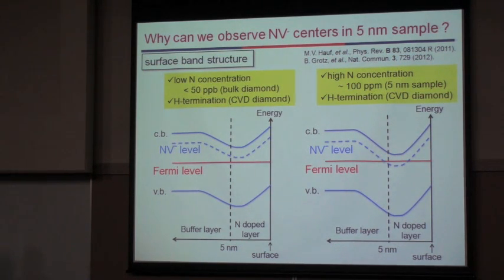So this is a very surprising result, because people believe the NV center cannot exist near hydrogen-terminated surface layers, because the NV center energy level is above the Fermi level in the hydrogen-terminated surface layers. However, we can observe the NV center in 5 nanometer surface layers. The reason is that the high nitrogen concentration in our sample pushes down the energy level of the NV center below the Fermi level. So the NV center can exist in a 5 nanometer surface layer, even for hydrogen-terminated samples.